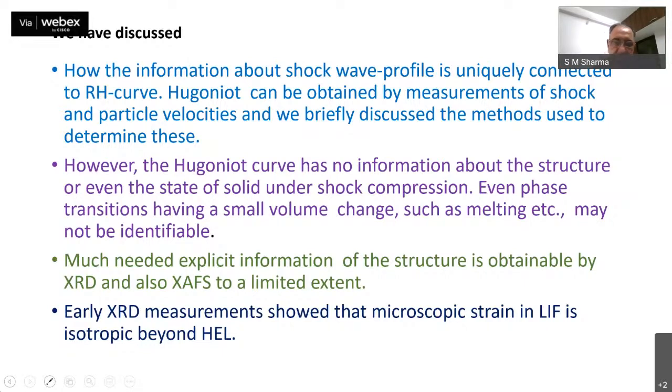We showed that in one direction, just 111, below the Hugoniot elastic limit, its shock compression indicated the uniaxial strain features, while in the 100 direction, beyond the Hugoniot elastic limit, it showed essentially isotropic compression, which means hydrostatic compression. And the reason for that we mentioned was because of elastic plastic deformation.